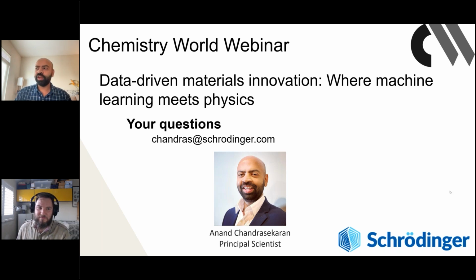So we don't do experiments ourselves within Schrödinger, but we always validate against experiments. The advantage of machine learning is that you can directly train machine learning models on experiments, and that's a beautiful part of it. All the chromophore data sets for the optoelectronic properties, the optical properties, the absorption wavelength, were experimental properties. The viscosity was also an experimentally measured property. The glass transition temperature was an experimentally measured glass transition temperature of a polymer. So we do see very good agreement between machine learning and experiments.